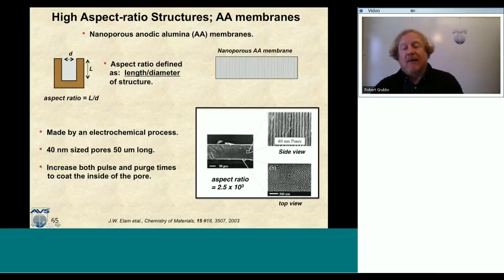And you can see in the top-down view that they're in a reasonably good array. You can see that they're pretty consistently sized pores. They're all about 40 nanometers in width, and they have aspect ratios of like 2 times 10 to the 3, so a 1,000 to 1 ratio. So they're 1,000 deep to 1 wide. That's actually a very aggressive aspect ratio for any deposition technique.